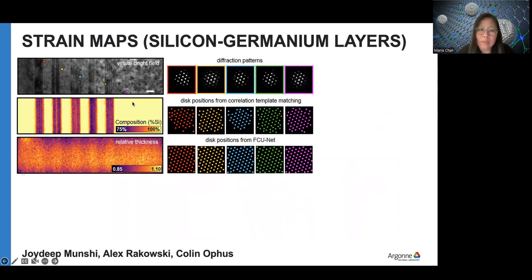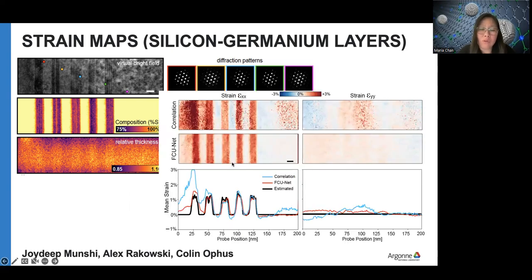With a trained model like that, we tested it on strain maps in real experimental data. So this is still sort of an artificial setup, the silicon germanium layers, and these are the CBED patterns. The positions obtained from correlation are shown on top, and the positions from the FC-UNet on the bottom. With that, we can work out the strain, and these are shown here, because the ground truth for the strain is obtained from EELS, because with the silicon germanium, we can work out the concentrations and deduce what strain to expect. And then the strain found from correlation is shown on top and from FC-UNet on the bottom. These are the profiles. You can see that there's a bit better accuracy with FC-UNet in the direction where you expect strain, and also slightly better in the direction where you don't expect strain, which is the vertical direction of this.